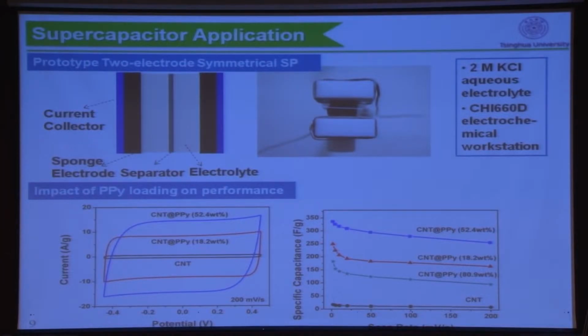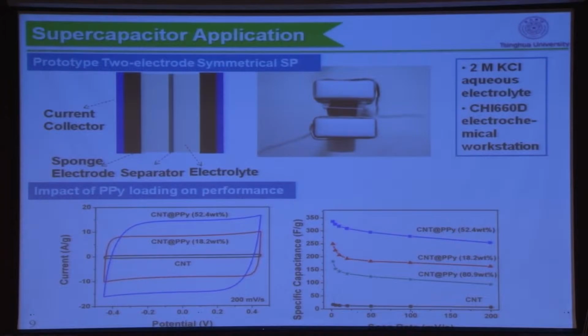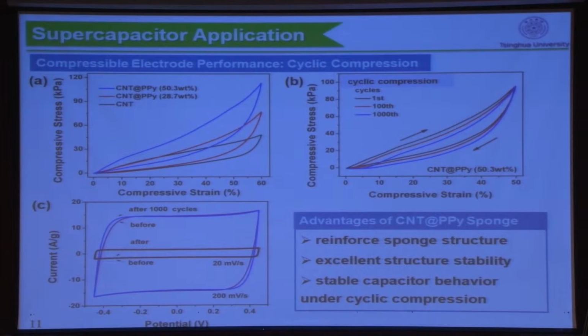The left figure shows the comparison between the CV curves of compressed bare CNT and the CNT-PPY sponge, and the right is the calculated specific capacitance. We can see that without PPY, the porous CNT sponge only has a capacitance within 25. Exactly, it's 17 farad per gram. And after PPY deposition, the highest capacitance can reach about 300. And about your other question, maybe this figure can explain. Before and after the compression is stable, the capacitances are almost the same.